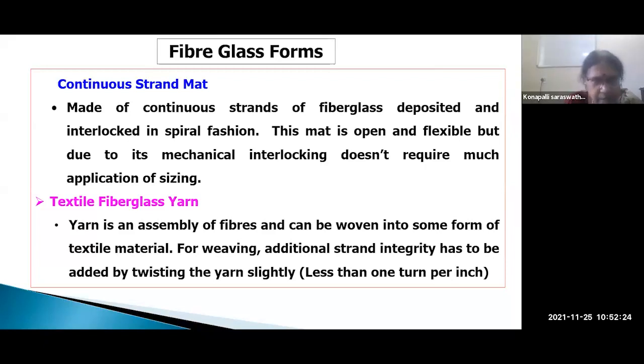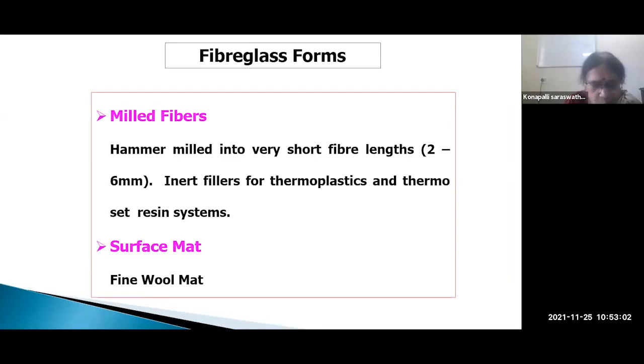Then textile fiberglass yarn. When we weave the fibers, for weaving directly with rovings, like roving weaving, it will be very coarse and all the fibers will not be put together. So if we apply a little twist, that is called yarn. Yarn is what we call it when we apply twist to the rovings in textile form. For weaving, additional strand integrity has to be added by twisting the yarn slightly. If we twist the roving by less than 1 turn per inch, it will be called yarn. And even for our cloth weaving, we first make yarn. That is why it's called yarn.